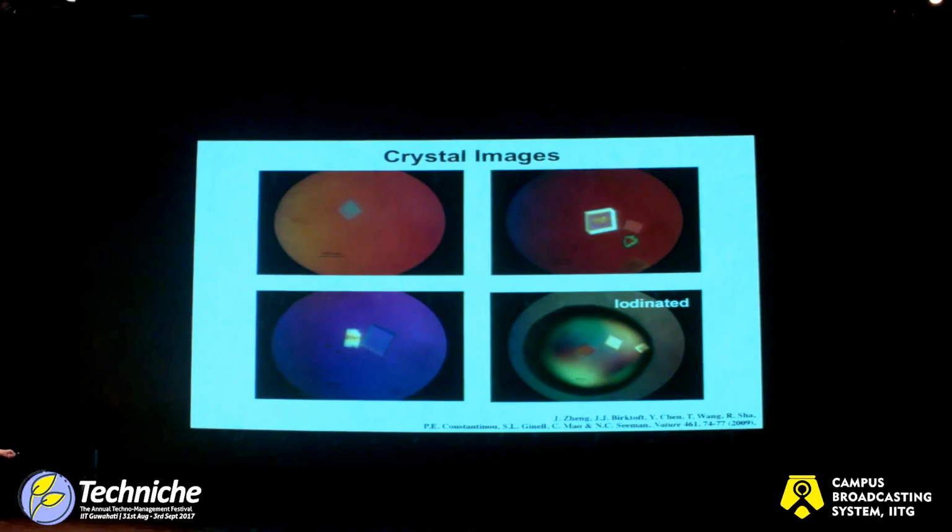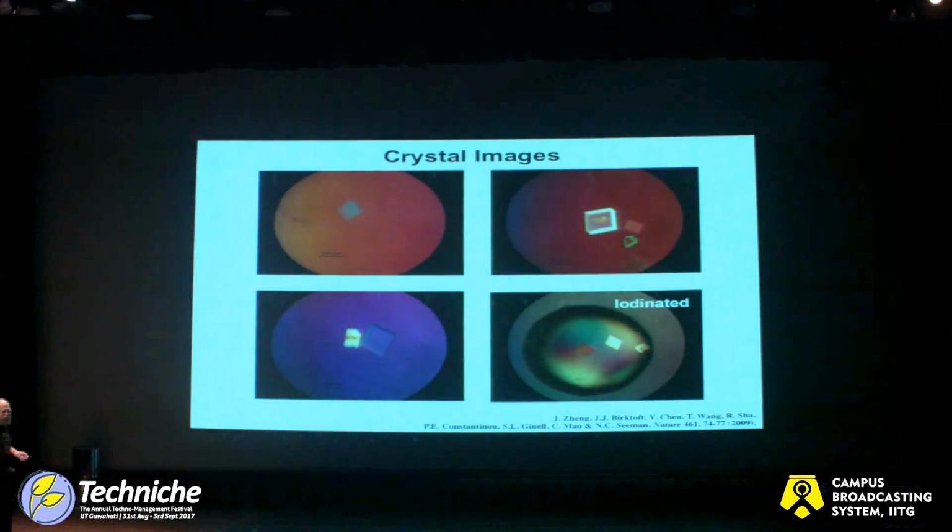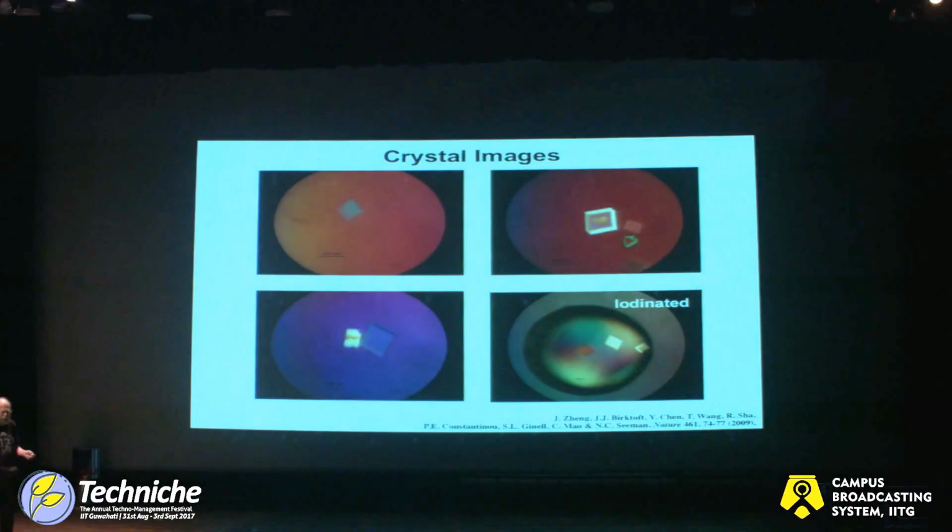Okay, so by putting these things just together in a pot, we were able to make macroscopic crystals. These are things you can see with your naked eye. They go anywhere from about 0.2 of a millimeter when they behave properly, all the way up to even a millimeter on occasion. You can see over here the scale bars are 200 microns. This is probably 300 or 400 microns across the diagonals here, and large crystals, and we know where all the atoms are because we put them there.